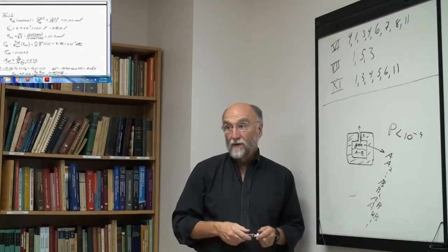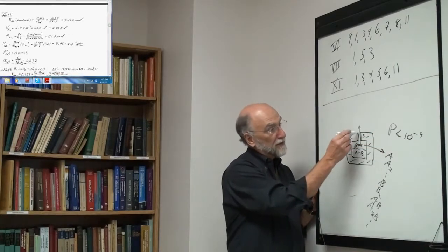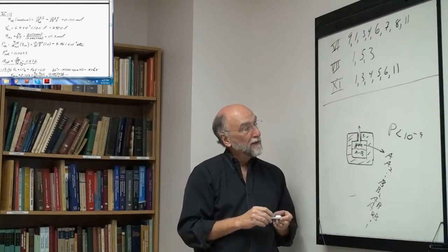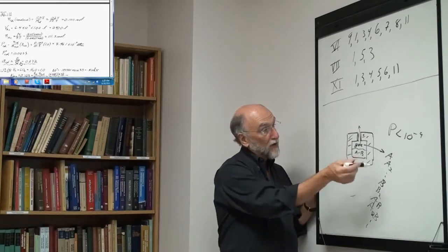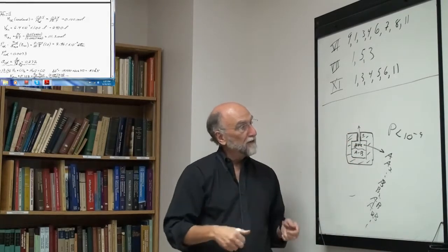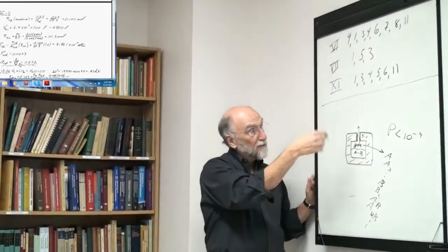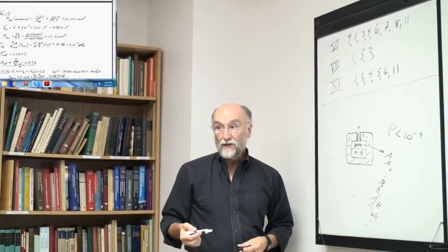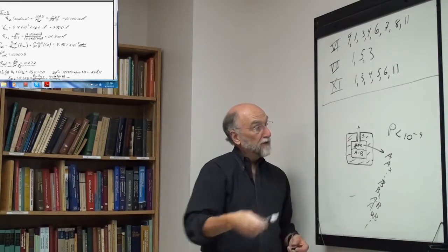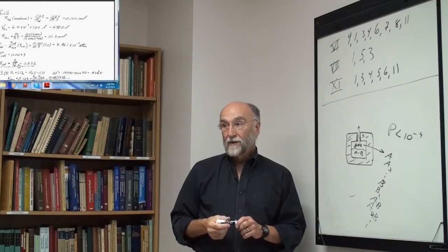And if the gas pressure is very low, there is an equation which relates the diameter of this and everything to a simple equation for the gas partial pressure of that molecule. If the gas pressure is too high, then you get collisions and everything. You can't really work out the number of molecules escaping per second as a function of the partial pressure. So the length of this thing has to be fairly short compared to the mean free path between gas collisions in order for the thing to work. That's why it really only works for low pressures.